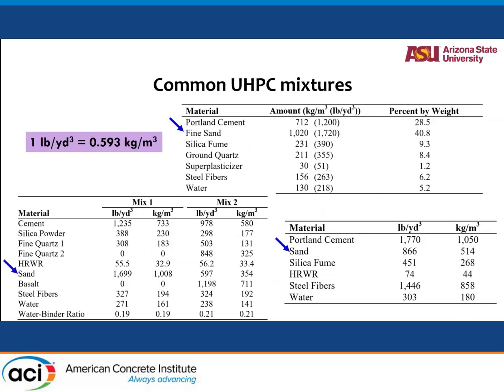So here are some common UHPC mixtures that are available in the literature, and you can see very high cement content, 700, 800 kilograms per meter cube, and a bunch of other things in sand. And you can see silica fume, ground quartz, steel fibers in some cases, all of that. Obviously, if you're looking at very high amounts of steel fibers and admixtures, the cost of your concrete is going to go up. So it's not surprising that typical UHPC mixtures have been costing 10, 15 times that of conventional concrete mixes. That is expected with all the extra expensive materials that you need, plus the fact that most commercial UHPC mixtures are proprietary mixes, so there is a little bit of added cost because of that.